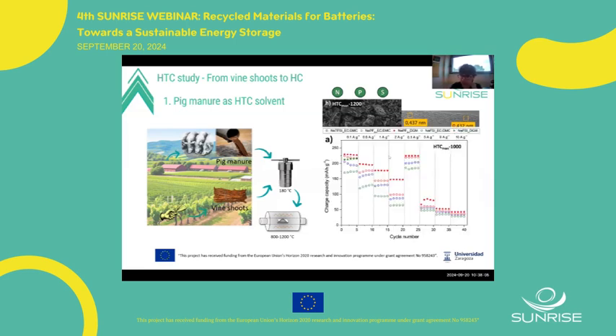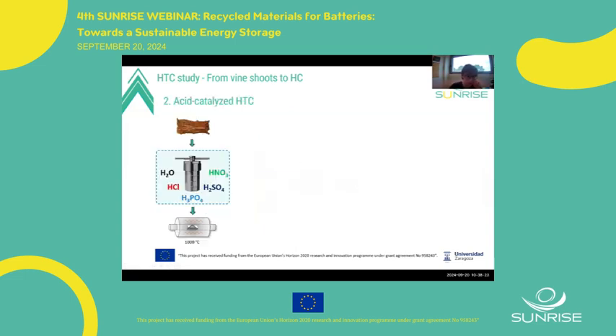When we checked this performance in half cells with different electrolytes, we obtained relatively high rate performance for this material, much higher than for hard carbons we produced only with water. The next step we performed was to add some acids to the water solution in order to promote several reactions.